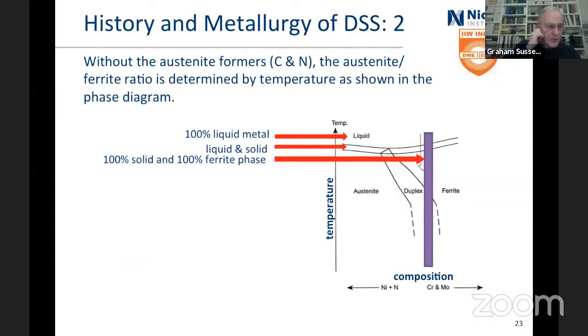Okay, why is it important? Well, let's just look at the straight austenite forming things, but leave out the carbon and leave out the nitrogen because they're not metals and they're quite hard to control. So then the austenite ferrite ratio is going to be determined by the temperature in this phase diagram. So for this level of nickel and these levels of chromium and so on, here you'd be austenite, there you'd be ferrite, and there you'd be duplex. You'd have some of each. And this phase diagram goes like that. So it's melting, it's all liquid, and then it starts to solidify.